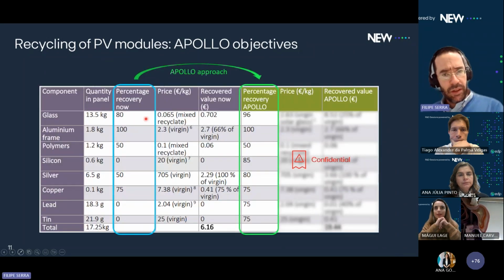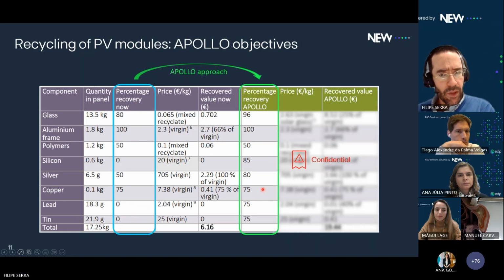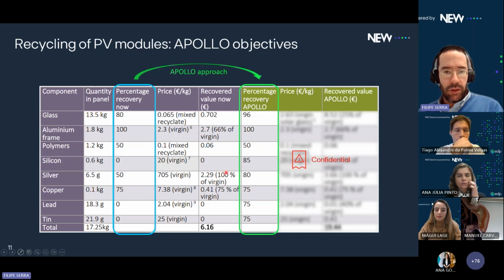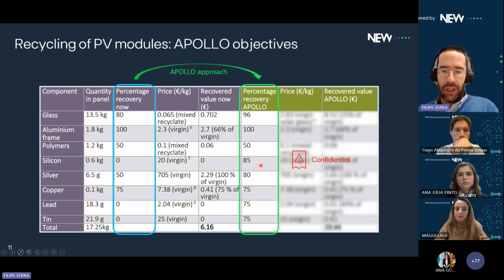So this is the current state of the art. We currently gather 80% of the glass. The objective is to get almost 100%. The aluminum frame, well, that's easy to recover, but the same for the poly, but the silicon, the silver, and the lead and the tin, we want to also recover and put back on the feedstock process. And one of the goals is to obtain that silicon here with a purity level enough to enter that silicon feedstock after the polysilicon production.